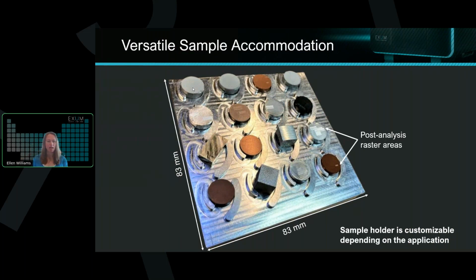And we can analyze anything that fits within this 83 millimeter by 83 millimeter area. So that could be multiple samples if you're doing a quality control application and verifying the chemistry of multiple batches of things. It could be one large material like we saw with the 100 millimeter tensile bars. Essentially, they just stuck off the edge a little bit here, and we didn't move the stage to hit the edge of our sample chamber. But again, a lot of versatility and minimal sample prep required.